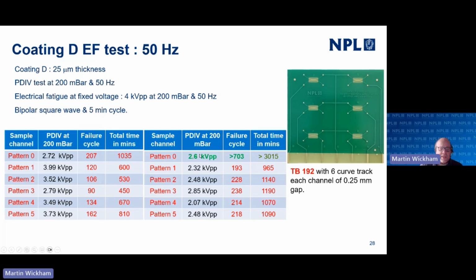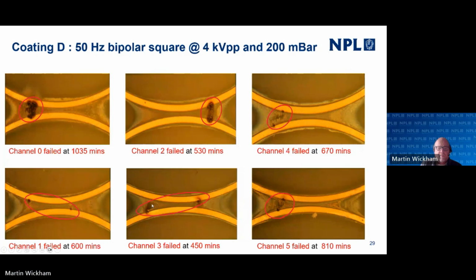But the other thing to note here is that it's not the sample with the highest inception voltage which has lasted the longest. There are samples here with much higher inception voltages, and they've failed. So, even within this sample, there is another track here with a higher inception voltage which hasn't gone to the full test time like this sample has. So it's very difficult to see any correlation between inception voltage and failure time.